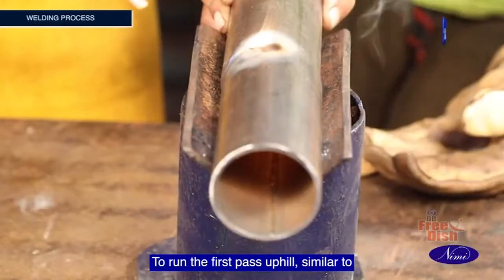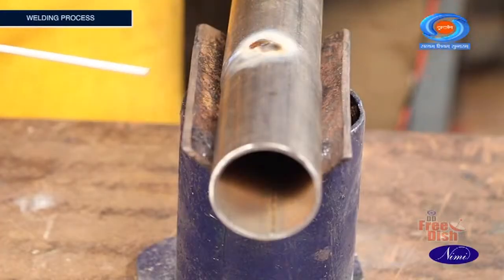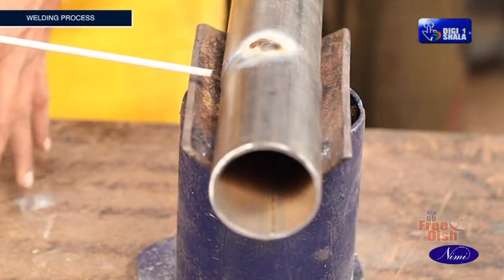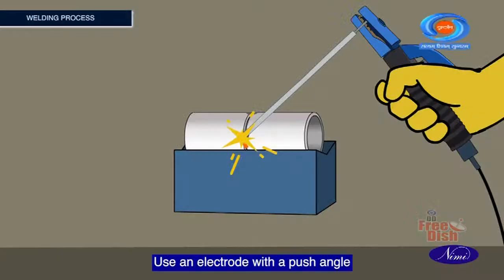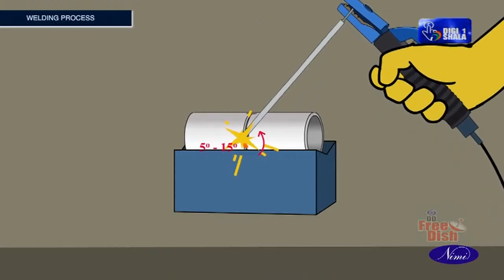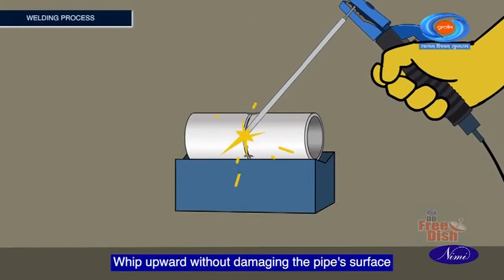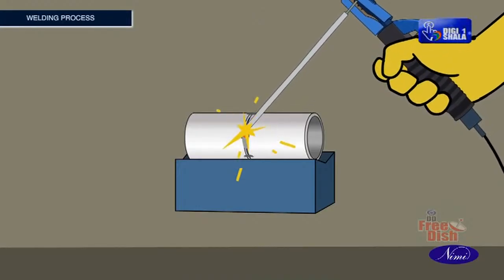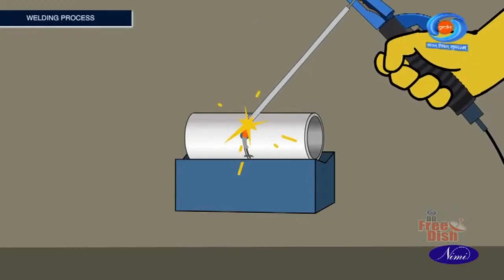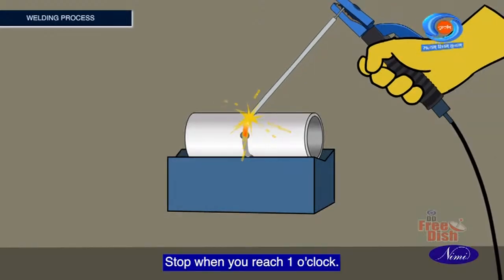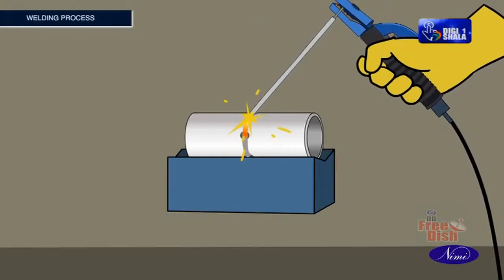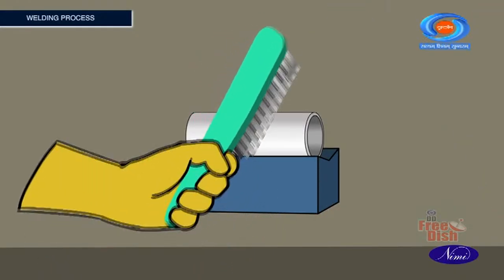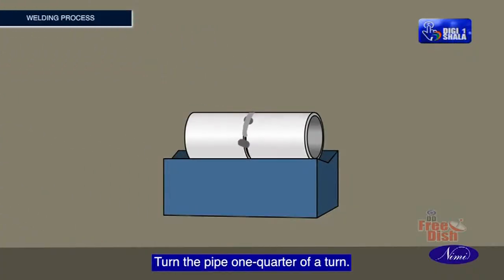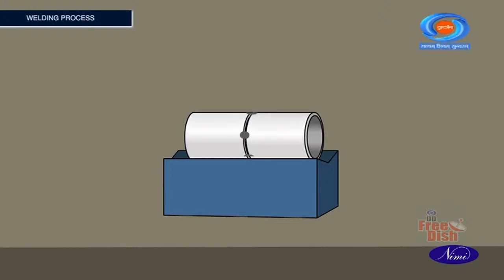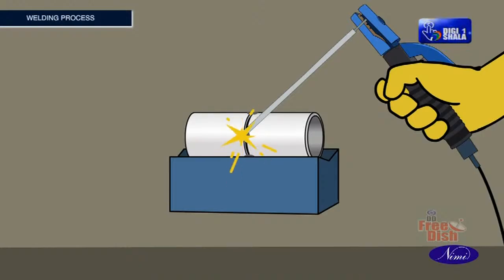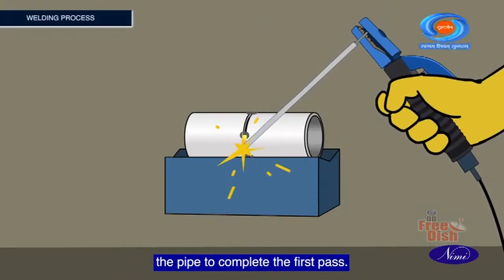To run the first pass uphill, similar to a welding plate in the vertical position, use an electrode with a push angle of 5 to 15 degrees upward. Whip upward without damaging the pipe's surface on either side of the V groove. Stop when you reach 1 o'clock. Clean the bead thoroughly. Turn the pipe 1/4 of a turn. Proceed welding in the same manner. Repeat this process for all 4 quarters of the pipe to complete the first pass.